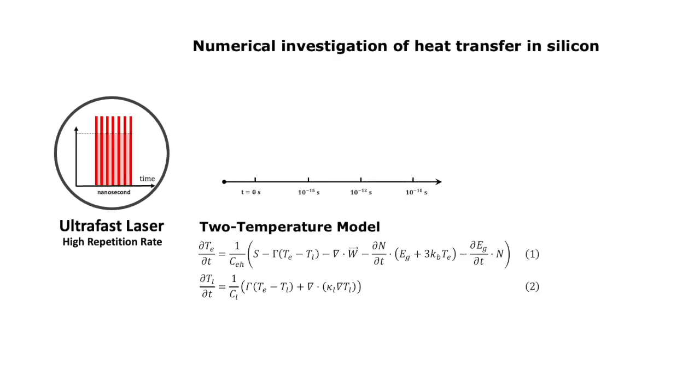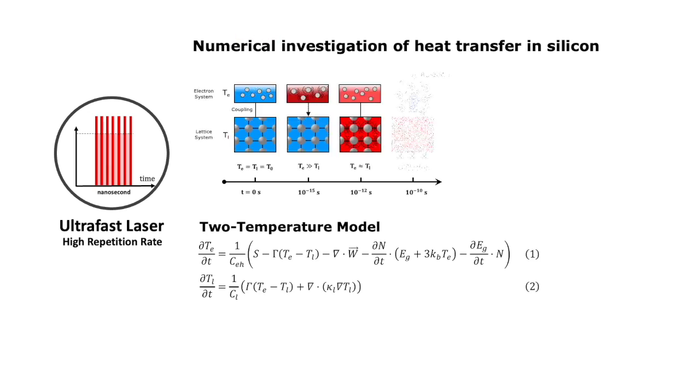We also perform numerical calculation using a two-temperature model and simulating the ultrafast ablation in semiconductor. A carrier generation equation was added to the model to correctly predict the electron and lattice temperature.